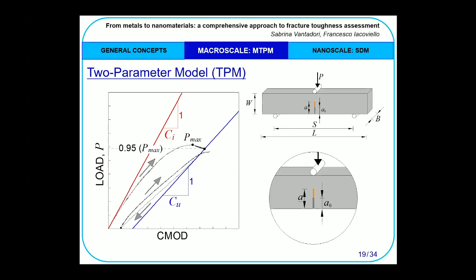The specimens have a prismatic shape and present a notch in the lower part of the middle cross-section. The specimens are tested under 3-point bending and crack mouth opening displacement control. More precisely, the specimen is monotonically loaded up to the peak load Pmax. Then the post-peak stage follows, and when the force is equal to about 95% of the peak load, the specimen is fully unloaded and then reloaded up to failure.